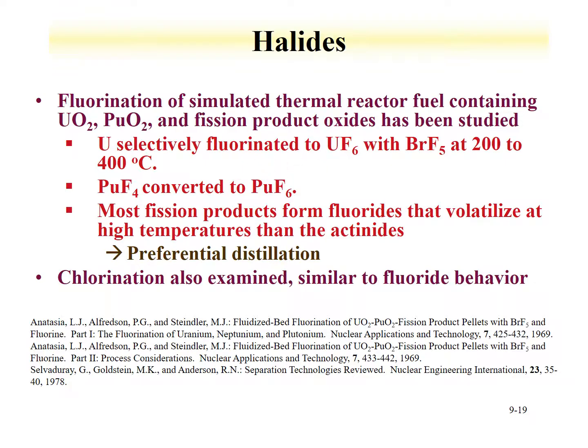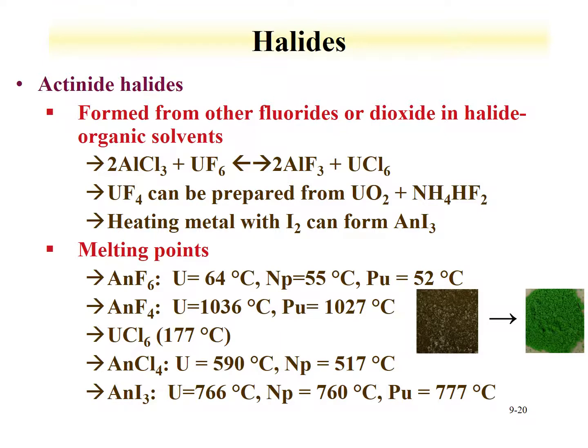And chlorination has also been examined, and trends are similar to the fluoride systems. Details on some of these fluorination processes are listed here. Some routes for forming actinide halides are shown below. One route has an exchange of fluorine with chlorine, using aluminum chloride as the chlorinating agent, and you make the uranium hexachloride. In this route, the uranium fluorides can be prepared by UO2 reaction with ammonium bifluoride, or by heating metals with iodine, you can form actinide triiodides.